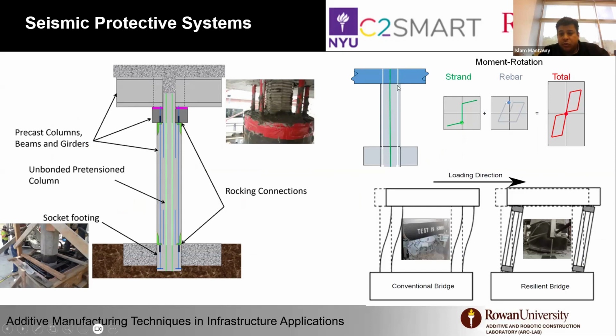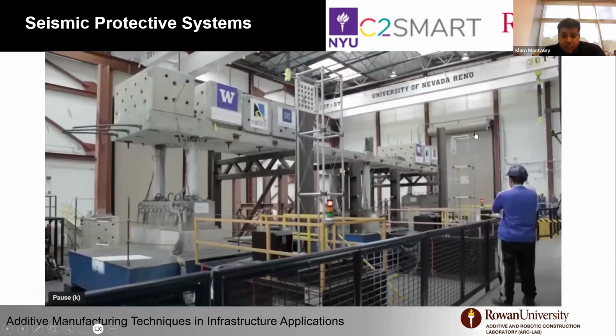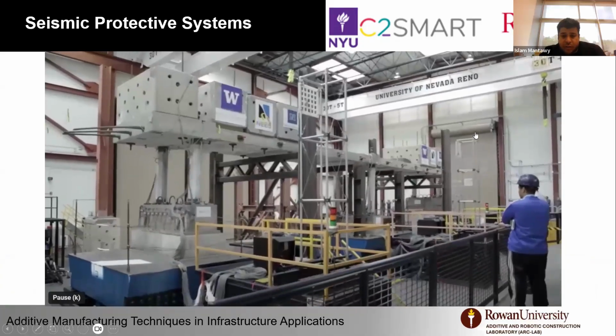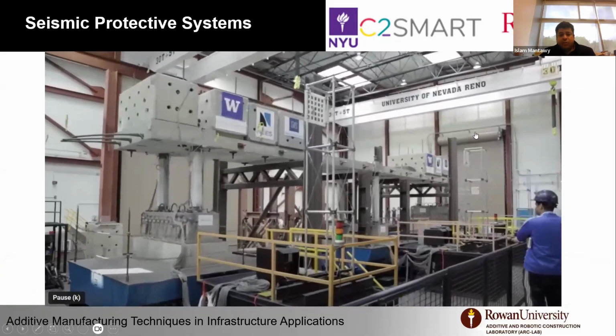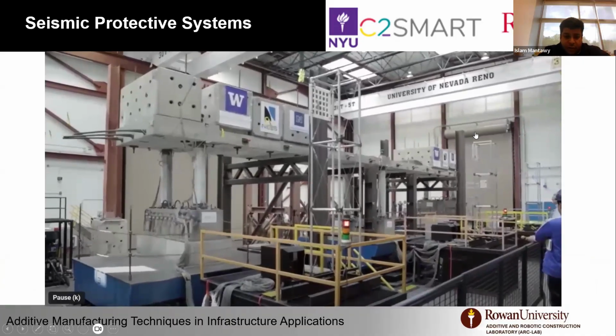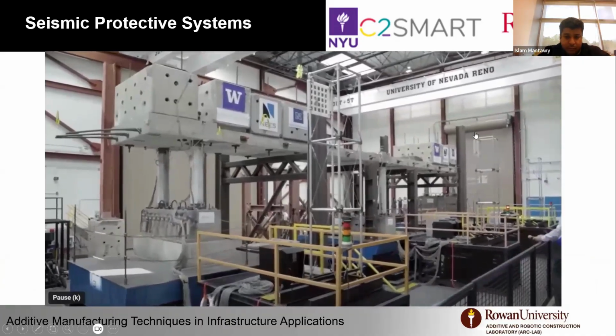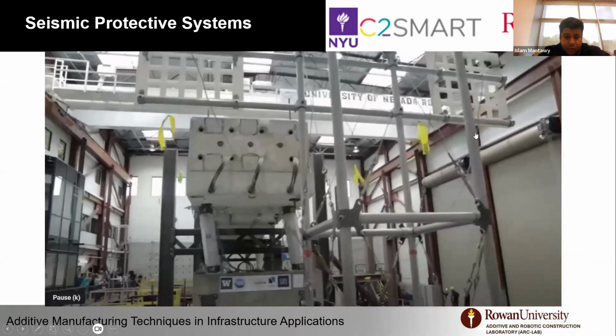Basically, the idea is to use pre-tension or pre-stressing strand in the middle, and use regular rebar to dissipate energy. The way the moment rotation curves will develop, as you can see here, is after you add them up, you can get the flag shape that self-centers the structure back. So we did test that bridge in 2014, and as you can see here, significant deformation, but after the end of the earthquakes, everything aligned very nicely to the vertical position.